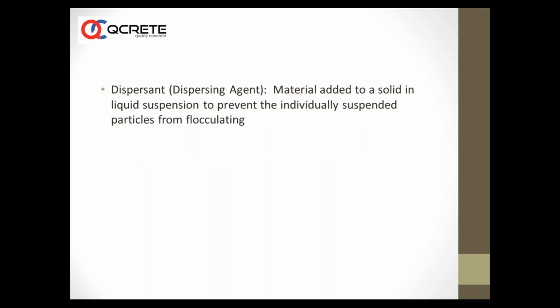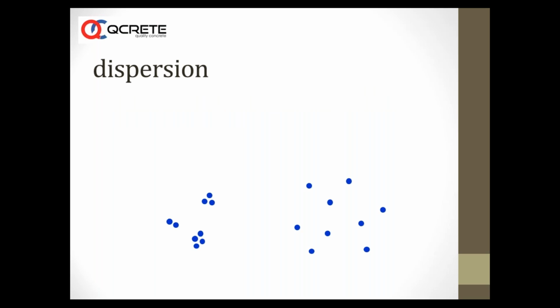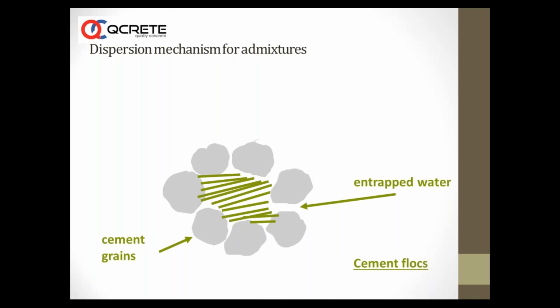So how do they act? Admixtures generally act like dispersants. They do not allow flocculation. For example, what happens when cement particles are there? You add water, some amount of water. Cement has a tendency to flocculate, the particles come together and they trap water. This water, which is trapped or entrapped between the cement particles, cannot express itself in terms of giving good workability to the concrete. This is a basic characteristic of cement. It traps the water when you add some amount of water, and hence you will not get the total amount of water which is already added to express itself as a fluid material.